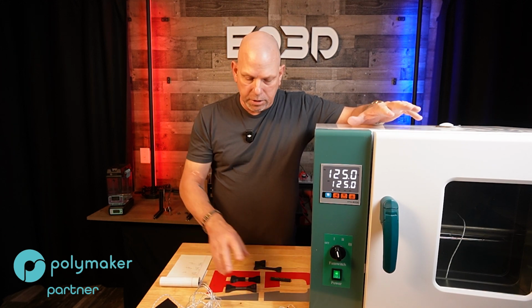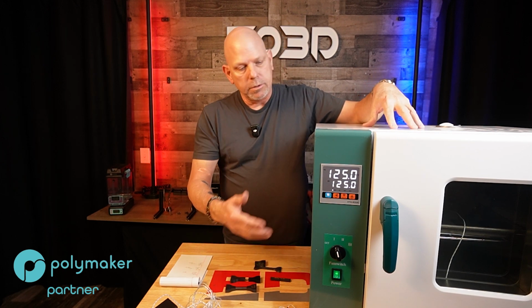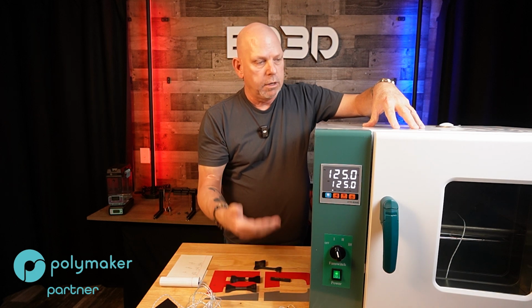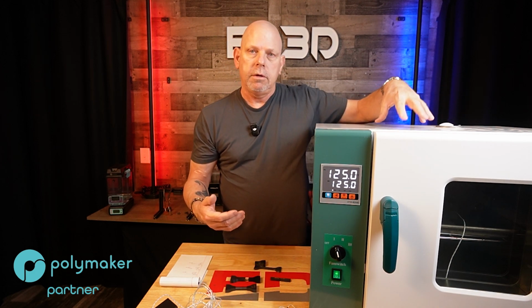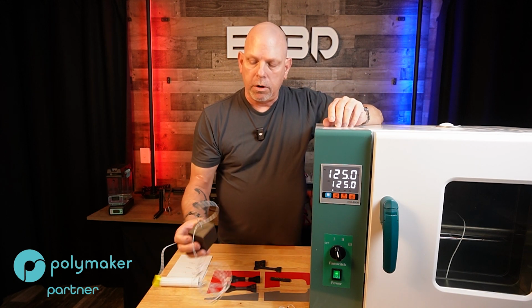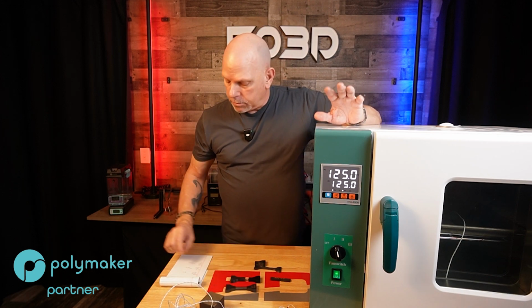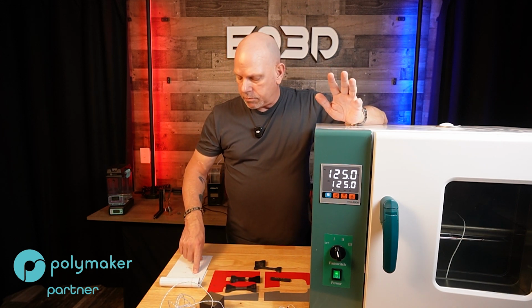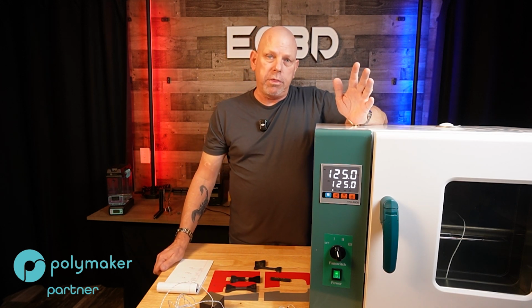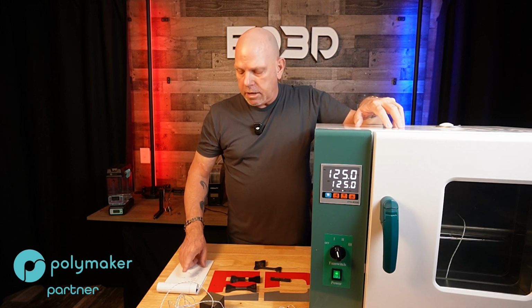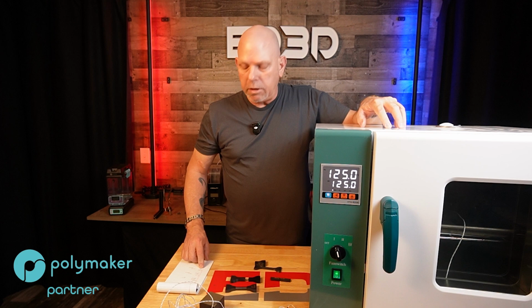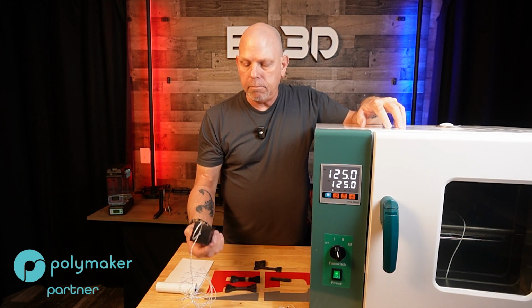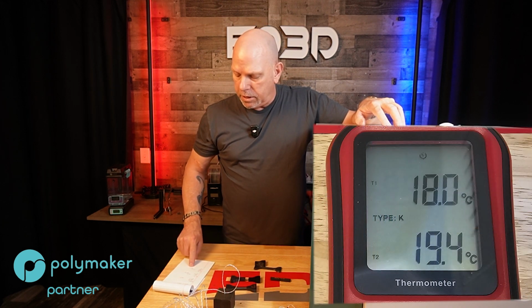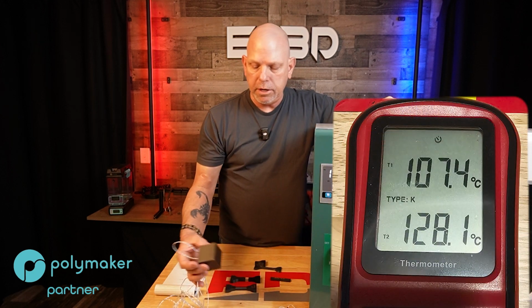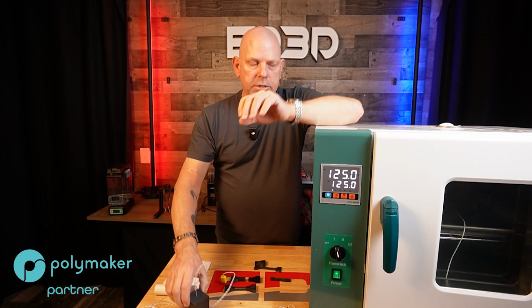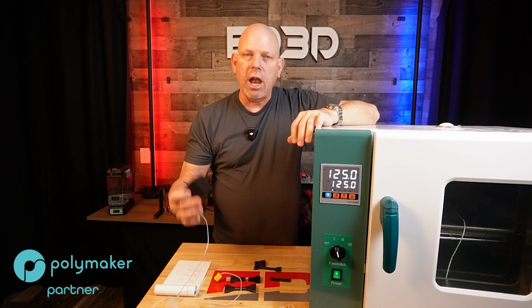Two minutes later, when I actually started recording, there's the temperature on the screen here. I have one thermocouple just in the middle of the box in here, and then I have one of these set up in there, and I was really surprised. I only took 3 samples from 9:06 to 9:35, so basically over a 30-minute period. We went from a 20-degree box to a 125-degree box. The core on this sample at the start was 18 degrees. At 30 minutes, it was 107.4 degrees. So the heat transfer, at least on PPS carbon fiber, got to the center a lot quicker than I thought it would.